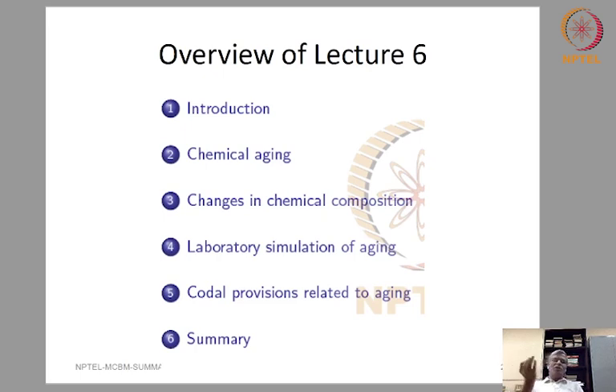To come from a different perspective, when you take bitumen, heat it, mix it with aggregate particles, and lay it in the field, there is some amount of aging that happens in the material, what we call the short term aging. As the material is exposed to the weather during its service, there is another kind of aging that happens, which is called the long term aging. So there has to be some simulation done in the laboratory to find out the state of the material at different stages in its service period. Only then can we make some statement about the expected performance of this material.